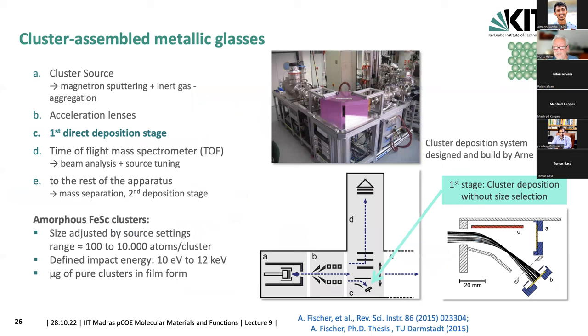And the idea was now, if we make the clusters, the particles which we assemble, smaller and smaller, then the fraction of this interfacial region, which I just described, should become larger and larger. And so we tried this in our first deposition stage.